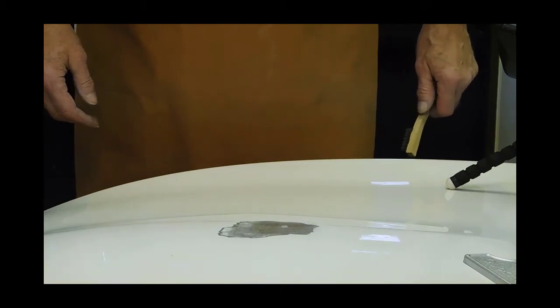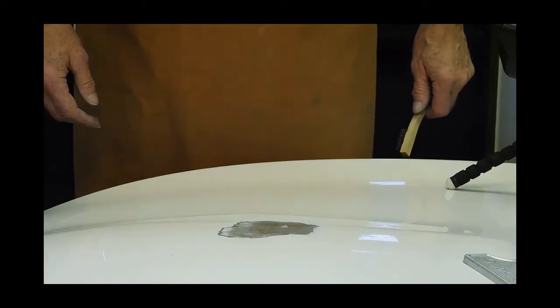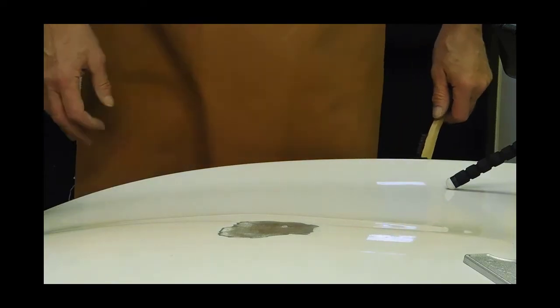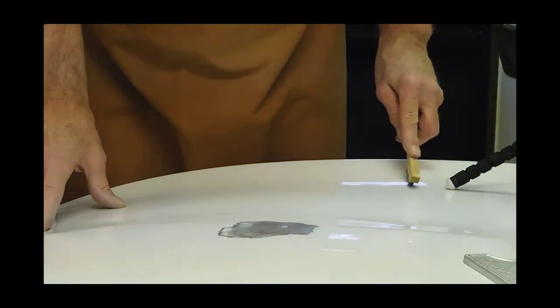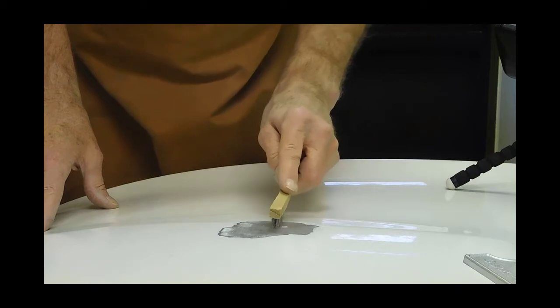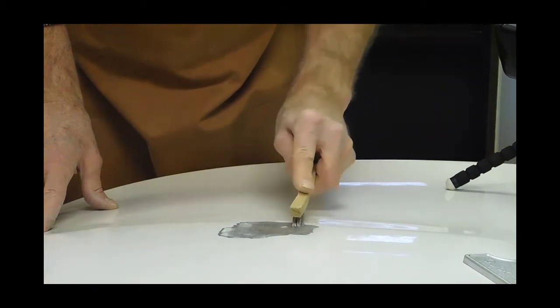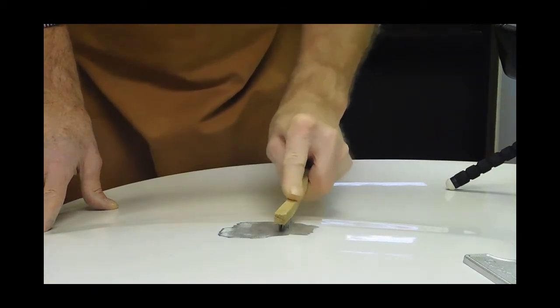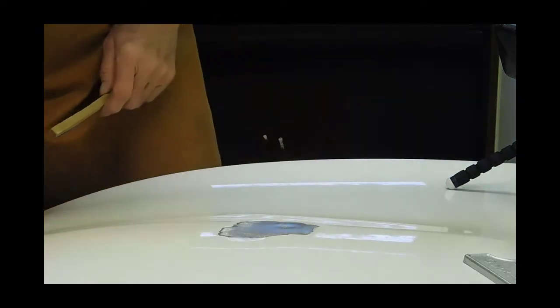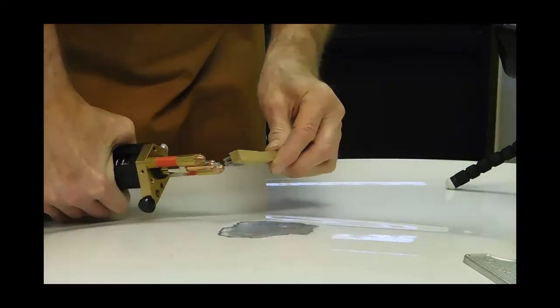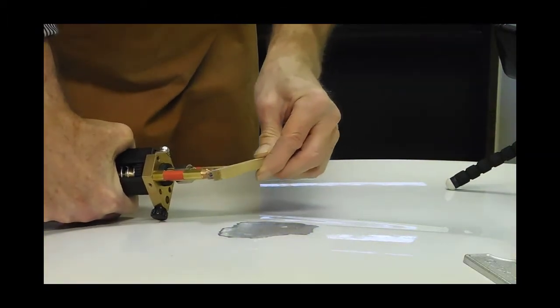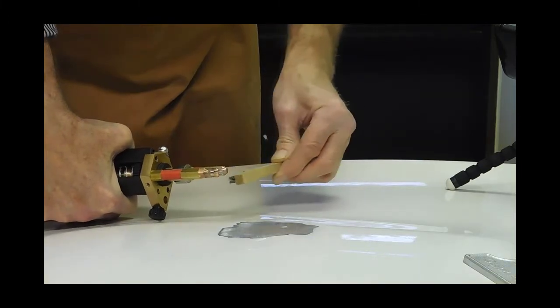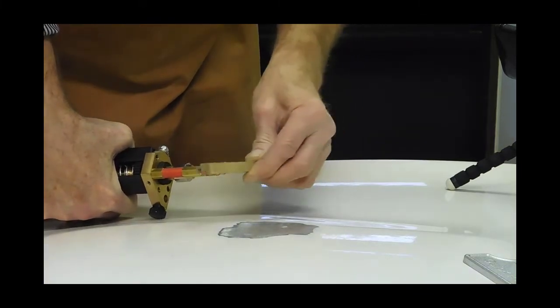During the welding process, we need to make sure the panel surface is free of all coatings and oxidization. If the paint-free panel has been exposed to air for longer than 15 minutes, it will need to be cleaned with a stainless steel wire brush. You must use a stainless steel brush. The use of a regular steel brush could result in contamination of the panel surface. The tip of the stud will require cleaning as well.